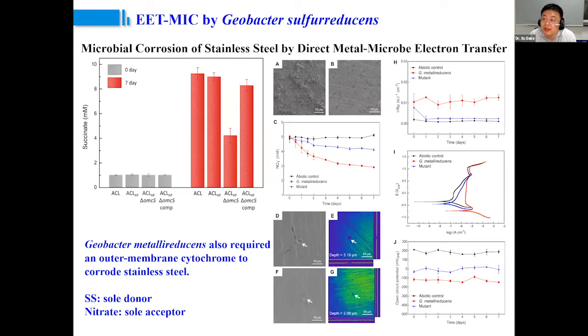Hey, you only tested one species, so you cannot claim it's a common theory. And then we found another strain. This is called Geobacter metallireducens. And we did the same experiment. We made stainless steel the sole electron donor, and because Geobacter metallireducens cannot reduce fumarate, we used nitrate as the electron acceptor. We repeated the same thing, making the same mutant by deleting the OmcS genes. We found the same thing: when OmcS is deleted, the corrosivity disappeared. And when we complement it back, the corrosivity recovered.